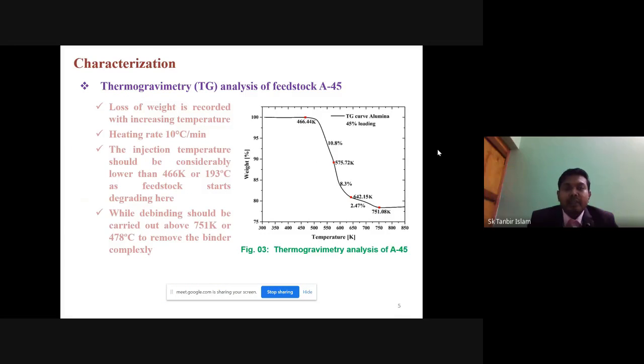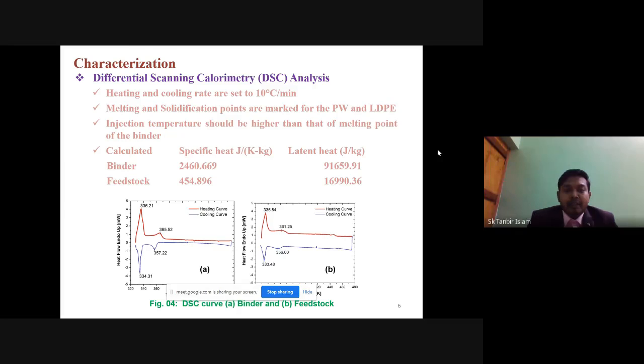TG analysis. Here, loss of weight is recorded with increasing temperature, and we found that at 193 degrees centigrade, the feedstock starts degrading, and above 478 degrees centigrade, there is no change of weight loss. That means there is no binder present in that feedstock left to degrade. DSC analysis. From DSC analysis, we can find the melting and solidification points of that binder and feedstock as well. And from this DSC analysis, we can calculate the specific heat and latent heat of solidification, as it is more important than melting for our binder. Here we have calculated these values.